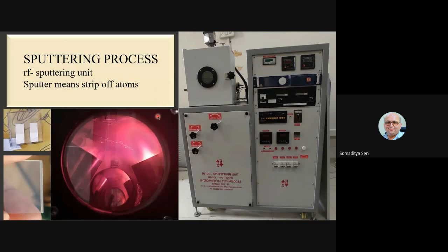So the last thing that I wanted to discuss, in the previous one, we're now into the thin film preparations and into the device area. So we have this RF sputter in our lab, where you can see what happens in RF sputtering. Sputter means stripping off atoms. So you have a target, which is the material that you want to deposit. You bombard it, and it strips off atoms and forms a plasma. And then you can see the plasma here. This is called the plume of the plasma.